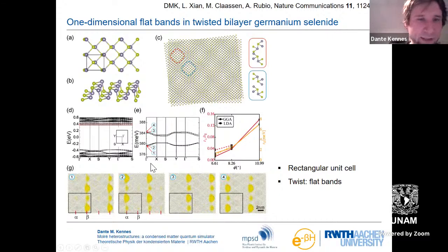Now, this is also reflected if you look at the wave functions. If you look at the wave functions, for example, at the gamma point, shown in these four panels below, for these four bands you see the charge distribution, the wave function squared, and they perfectly align along these one-dimensional channels here. So these are all one-dimensional, meaning that what we have done here is we have taken two-dimensional systems, put them on top of each other at a small twist angle, and what you effectively engineer at small twist angles is a one-dimensional system. So this is an alternative inroad in engineering effectively one-dimensional systems.